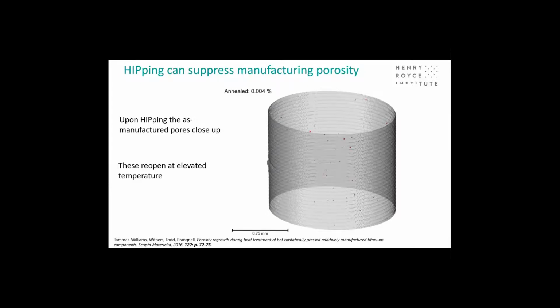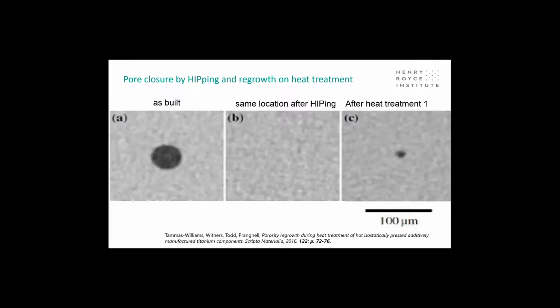Now we can see that those were in the locations of the original pores if we look at particular regions of interest. So here we can see exactly the same region of interest viewed in the as-built structure, where we can see a pore of about 30-40 microns in size. We can see that after hipping, that pore has largely disappeared, but we can also see that after heat treatment, that pore has reopened, and you can see a pore, albeit somewhat smaller than the one that we started with. So it's important to understand the way in which pores can be reduced by hipping, and to make sure that those pores simply aren't just closed, but they really are removed.